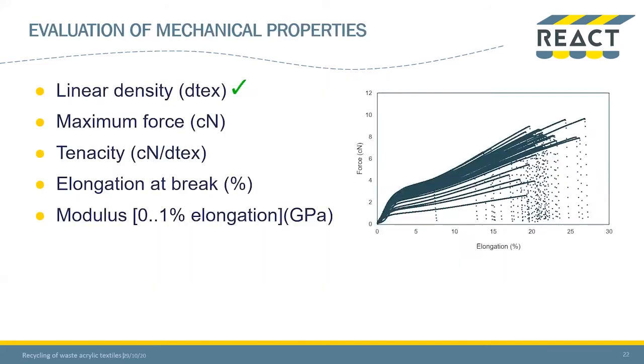And for this process, the impact on the mechanical properties was also very limited. A small decrease of 1 or 2% was noticed for the maximum force and tenacity for some of the experimental runs, which is limited, and compared to the mechanical recycling, this can be disregarded since we expect that mechanical recycling might induce a bit more damage. The elongation at break and modulus stayed the same or even slightly improved compared to the original acrylic fibers.